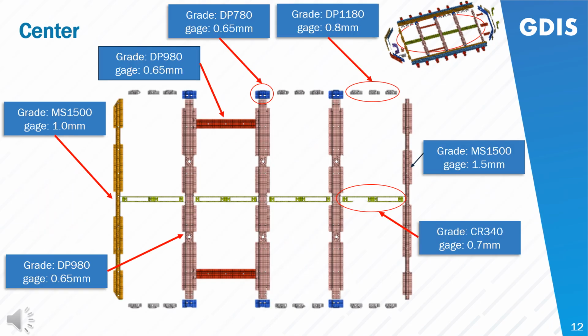In the middle structure, which is the center structure, you'll note that the forward and rearward cross members are actually martensitic 1500. The front is 1.0 millimeter thick and the rear is 1.5 millimeter thick. The fore-aft green parts that are shown here are basically CR 340, 0.7 millimeter, and the cross members shown in the middle are primarily DP 980, 0.65 millimeter thick.